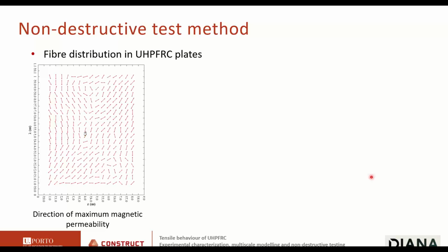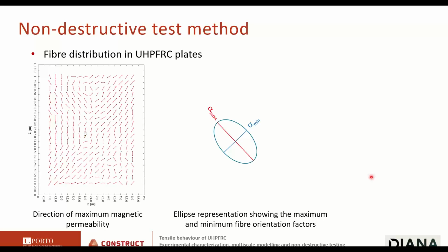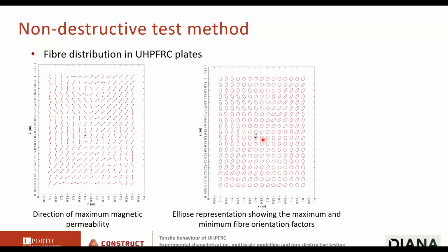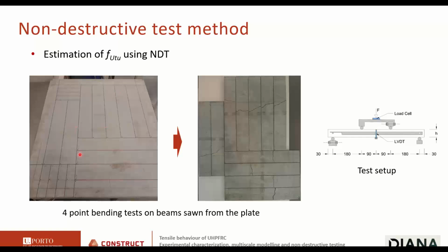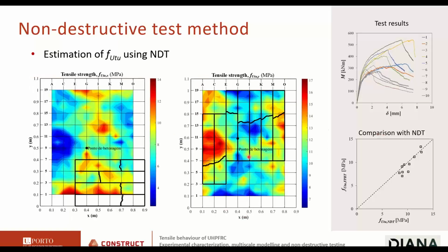Using the tensorial approximation, we can even plot the directions of maximum magnetic permeability, which should coincide with the directions of maximum fiber orientation. We can also represent this using ellipses, where the radiuses of these ellipses are proportional to the fiber orientation factors. We cut some plates from this large slab and tested them under 4-point bending, and this is where the cracks appear. So I plotted here the locations where the governing crack appeared, with the NDT-based estimates of the tensile strength in the horizontal direction and in the vertical direction. And you see that the cracks appear where the tensile strength is lower.